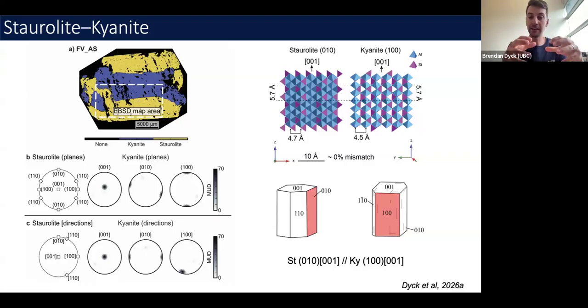And the best way of defining this is with this plane-direction notation. So we should have at least one set of planes between the parent and the daughter that are parallel. In this case, we can look at the 010 of the staurolite and the 100 of the kyanite. And then we should also have a set of directions that are parallel. In this case, we could look at the C axes of staurolite and the C axes of kyanite, right? And so that would be our definition of that relationship.